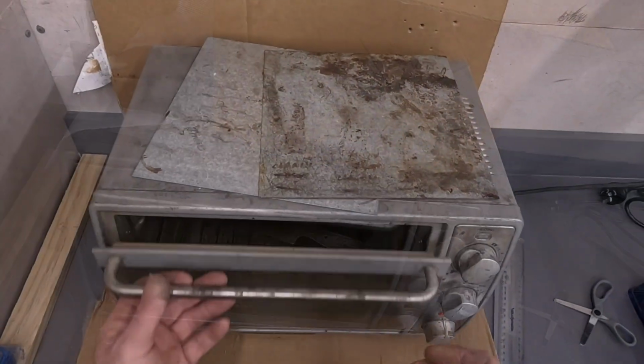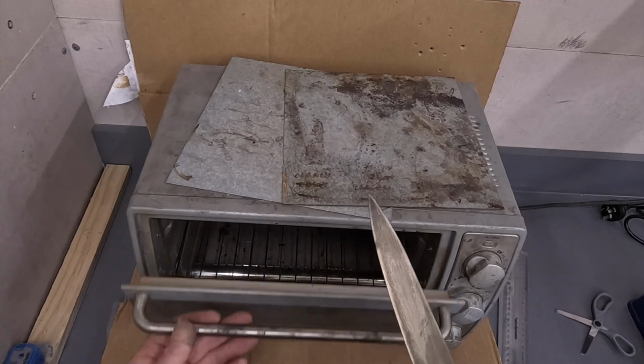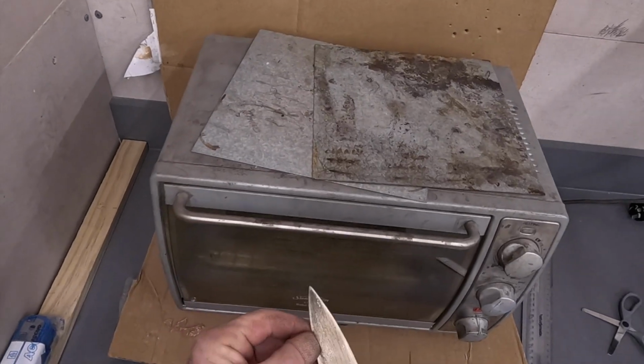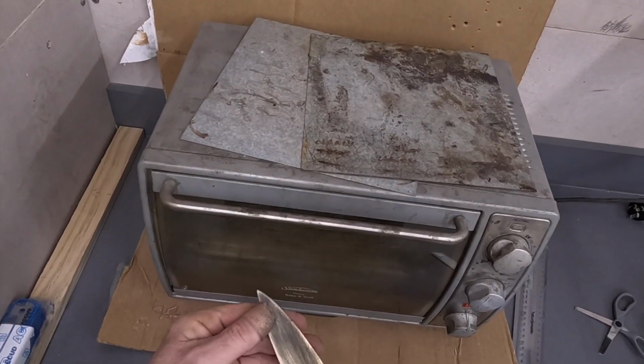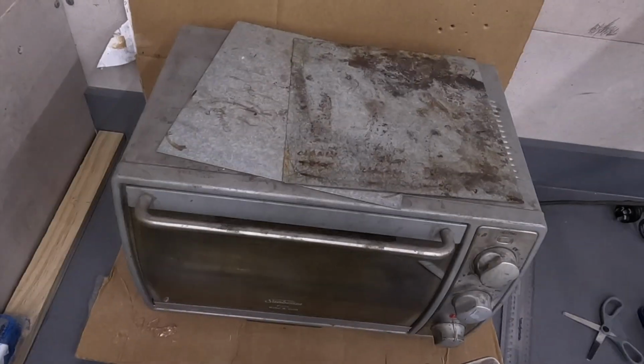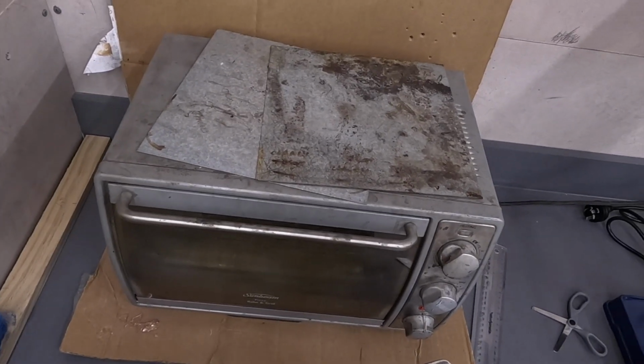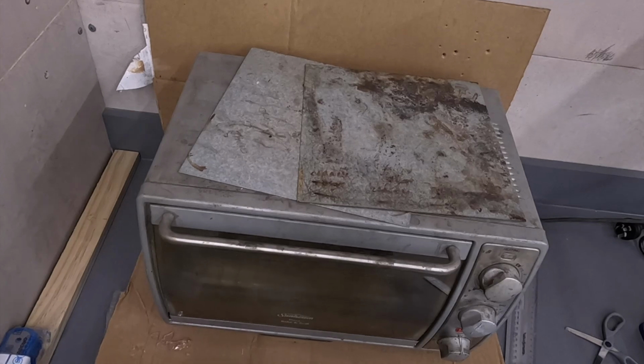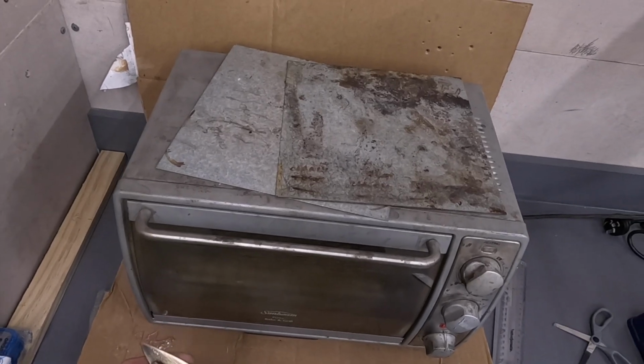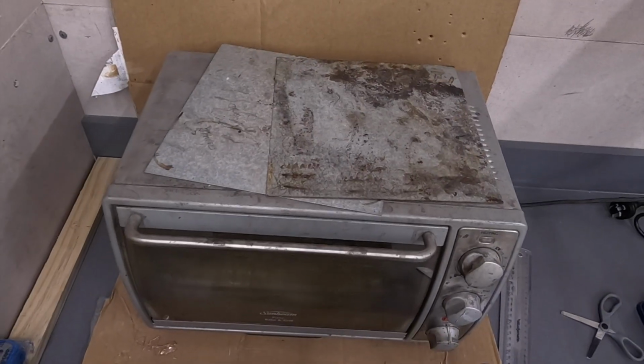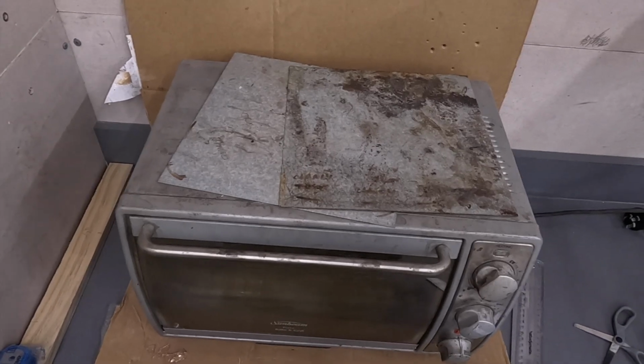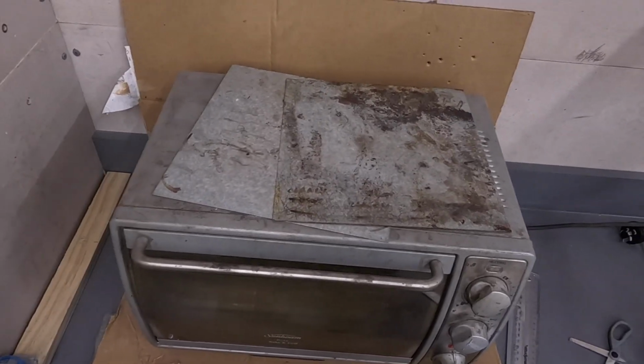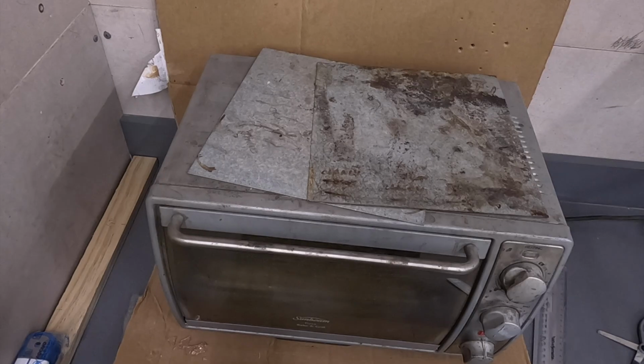if dropped. After 2 cycles in the oven to temper the steel, it should come out this beautiful bronze colour, or straw colour it's often referred to. If the knife is still a silvery colour, the temperature hasn't been high enough, or if it's turned bluey purple, the temperature has been too high. I suggest 200 as a starting point, but you'll need to play around with your own oven and mark the perfect point at which this straw colour occurs.